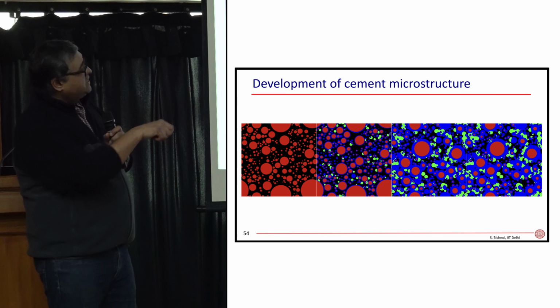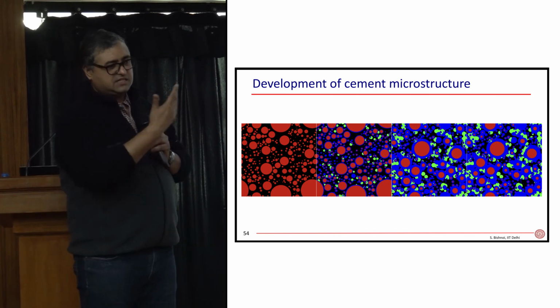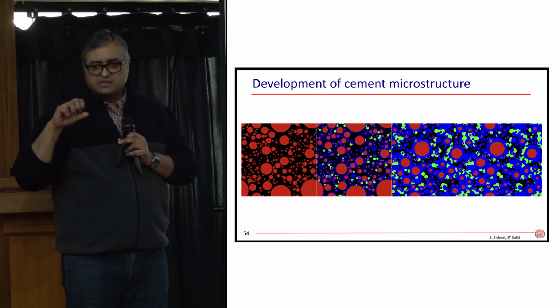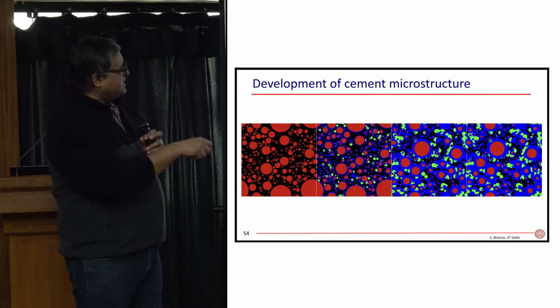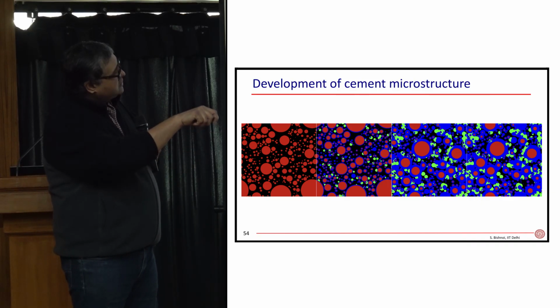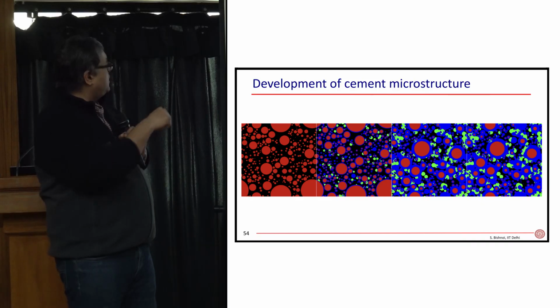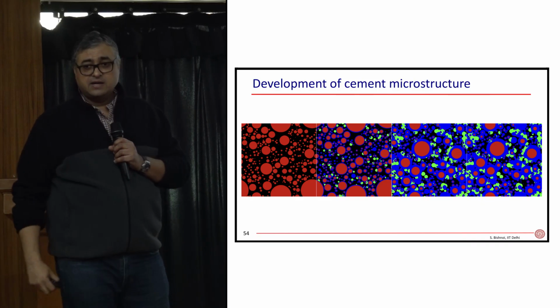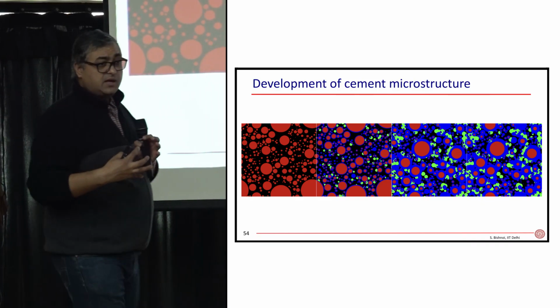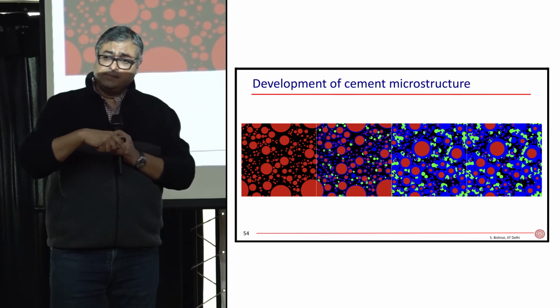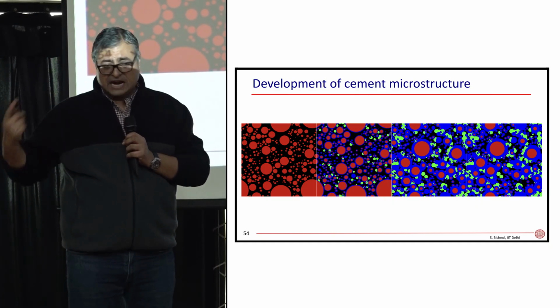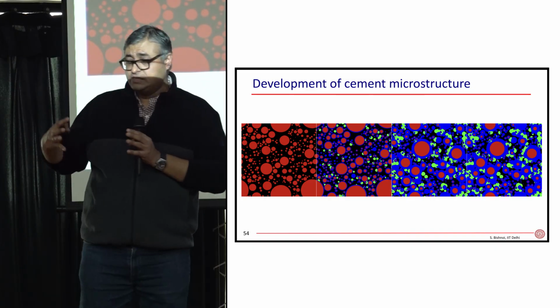There is more of the blue and green, which are the products—let's say the CSH and CH—that is produced. They deposit at various places inside the microstructure, hold these particles together, reduce the pores, reduce the empty spaces in between. They hold not just the cement particles together but also the aggregate particles and sand particles together, giving the concrete its strength.